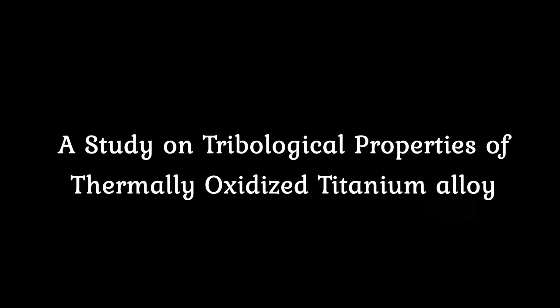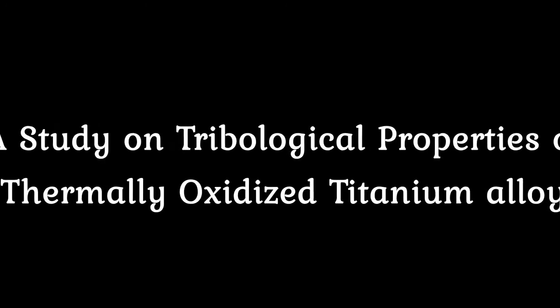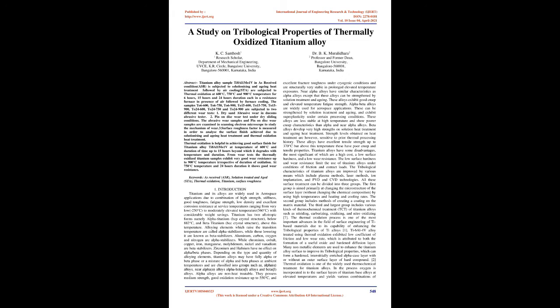A study on tribological properties of thermally oxidized titanium alloy. Abstract: titanium alloy sample Ti8Al1Mo1V in as received condition, ASR, is subjected to solutionizing and aging heat treatment followed by air cooling, STA, and then subjected to thermal oxidation at 600 degrees Celsius, 750 degrees Celsius, and 900 degrees Celsius temperature